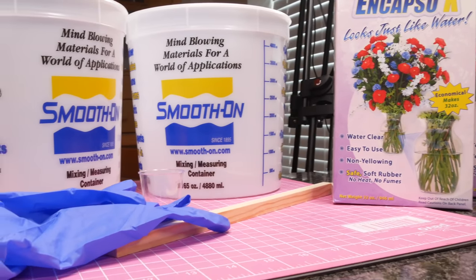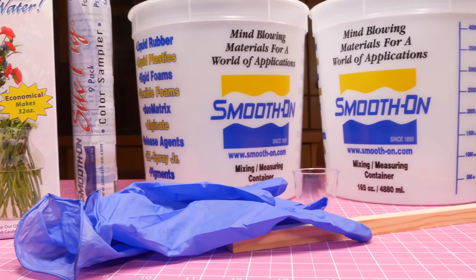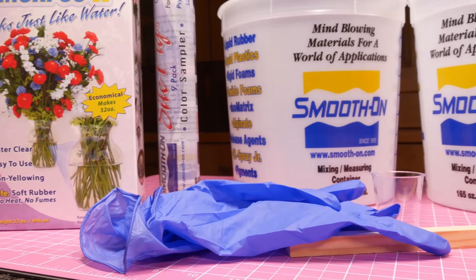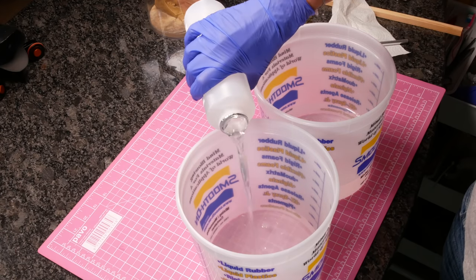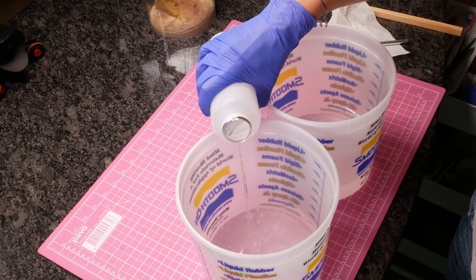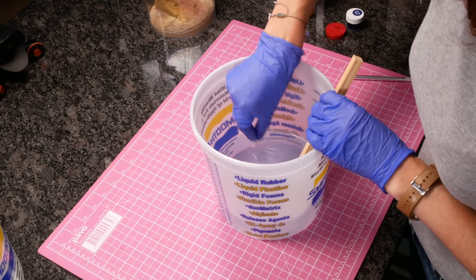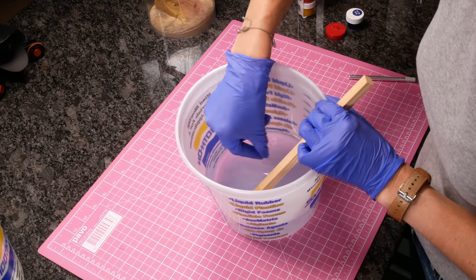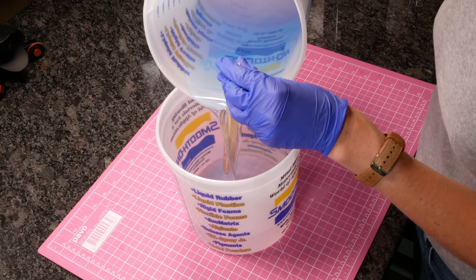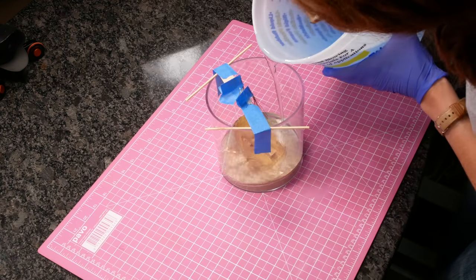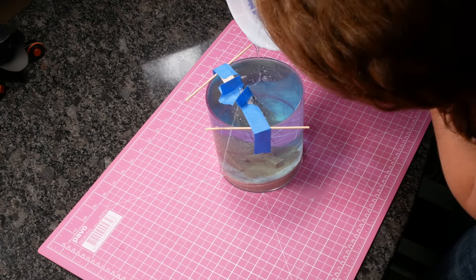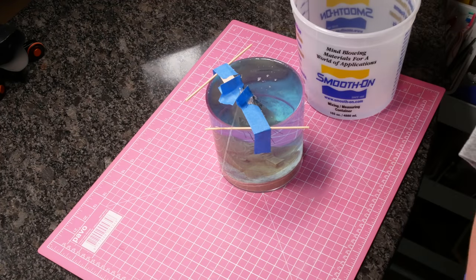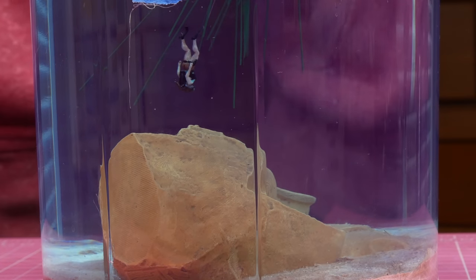Now the fun bit, rubber water. So why not epoxy resin? Well this doesn't heat up, you can do the whole pool in one go and it's really simple to use. I did just over two liters, hence the massive buckets, and measured it out. It's equal parts A and B with a little bit of blue tint. You put this in one half so it needs to be twice the strength that you want. I only want a gentle tint, you saw my test piece. And then you just fill it up. The bubbles magically go. It's not like resin, there's no trapped bubbles, you don't need to blow anything, they go within a couple of minutes.